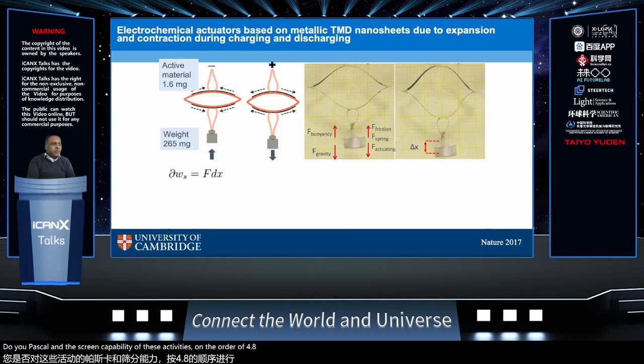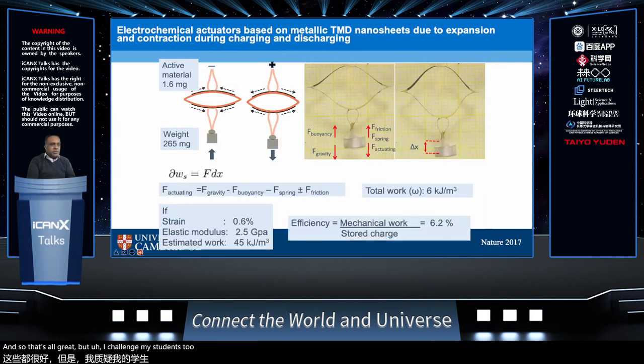And so that's all great, but I challenged my student to come up with a device that would actually demonstrate what these actuators were useful for. So he designed this bimorph actuator, which is completely jointless, just simply by patterning the MoS2 and cutting the substrate, which is polyimide, in the right way. You can actually make a little device which is capable of lifting weights. So the 1T MoS2 film is strategically placed in these black locations, as indicated here. And by intercalating and deintercalating, we can get expansion or contraction of the film, which leads to the lifting of the weight or releasing of the weight.